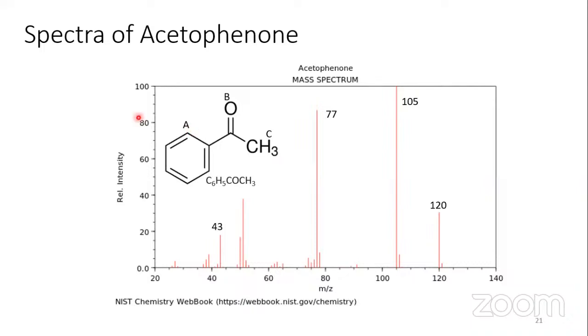Now, if you look at this spectra, it is called relative abundance versus m/z ratio. That is, the intensity of each ion is measured by considering 105, the highest peak in the spectra, as 100. And on the basis of that, the intensities of all other ions are calculated. So acetophenone will always have this kind of spectra, not only the masses, but even the ratios between 120, 105, 77, 43 will remain exactly the same. That's the advantage of the mass analyzer.